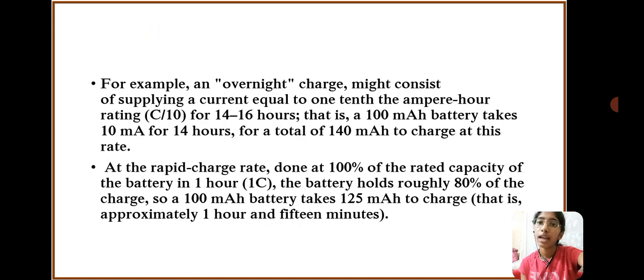For example, an overnight charge might consist of supplying a current equal to 1/10 of the ampere hour rating, C/10, for 14 to 16 hours. That is, a 100 mAh battery takes 10 milliamperes for 14 hours, a total of 140 milliampere hours to charge at this rate.